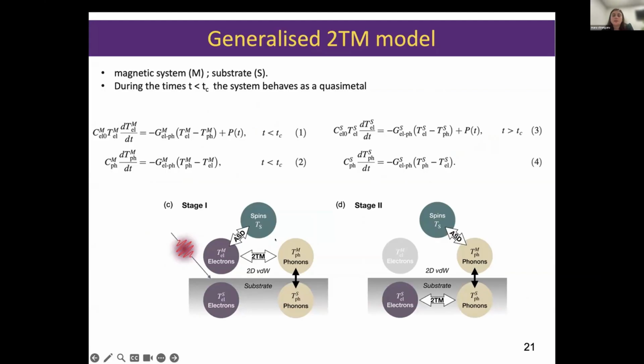We assume that our 2D system is within a kind of heterostructure form. So the 2D magnetic system lies on a substrate. Under laser excitation, the substrate is also heated and can exchange energy and heat with our magnetic layer. We have looked at the generalized 2-temperature model for a typical 2D magnetic system, chromium triiodide, which behaves as a quasi-metal. So for very short time scales, hundreds of femtoseconds, the laser excites the free electrons in our quasi-metallic chromium triiodide, as shown by this schematic here. And we're able to model the spins with our atomistic spin dynamics.